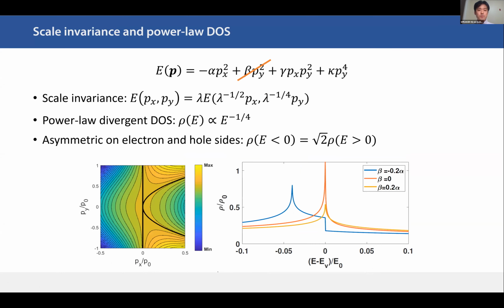And one may ask, what are the consequences of this high order Van Hove singularity? So again, we look at this effective model near this band touching point, and at the critical angle theta c, we don't have this second term in the right hand side of this equation. Without that term, we can establish a scaling invariance in this energy dispersion, which has this form. Based on this scaling invariance, we can directly find that this leads to a power law divergence in density of states, as we have seen in the multi-criticality of the Fermi surfaces in the introduction part.